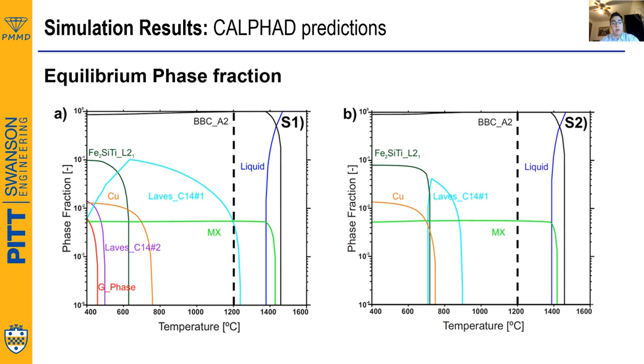Based on these, we then expect that for S1, the homogenized microstructure should only consist of the BCC ferrite with a very minimum amount of Laves with MX, and in the case of S2, the ferrite should only be accompanied by the MX. At this point, it's relevant to point out that when CALPHAD models, for example, the L21 phase, it does it as a line compound, like a line stoichiometric compound. This means that the L21 phase is assumed to have no solubility whatsoever of any element. And this is going to be important now, moving on to the experimental results.